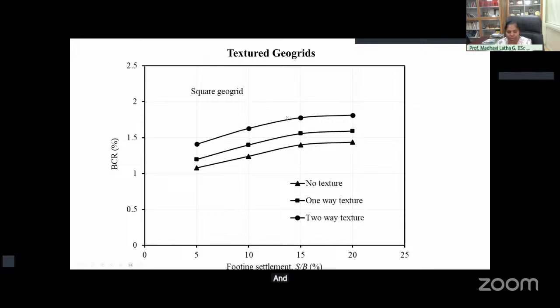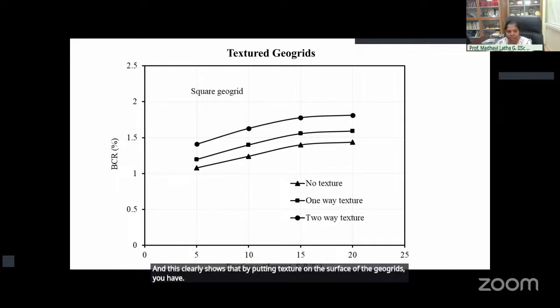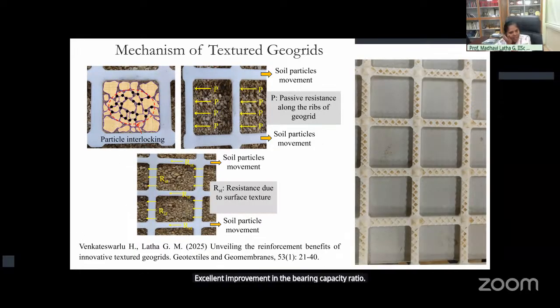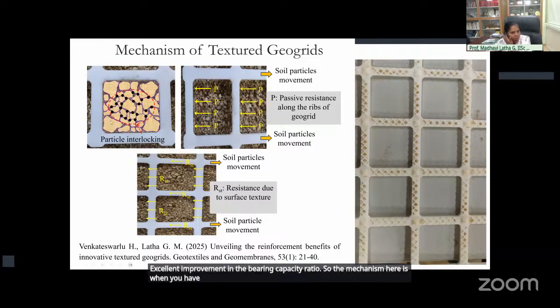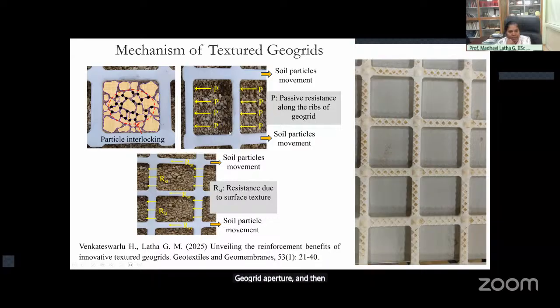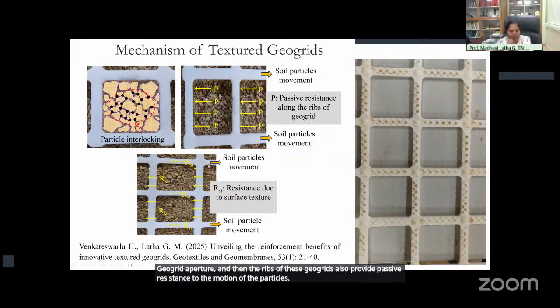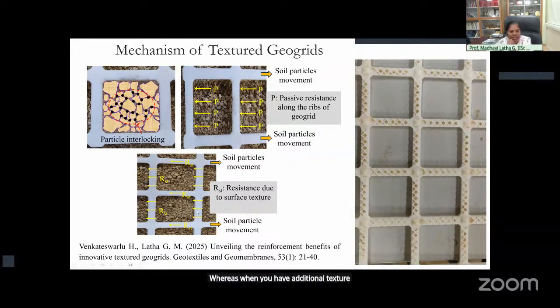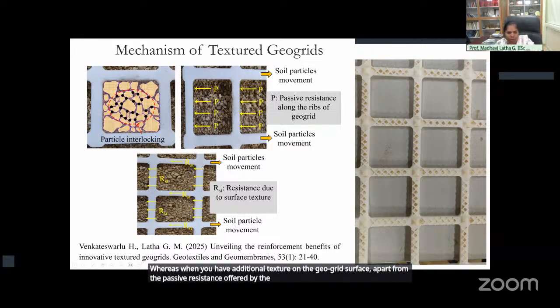And this clearly shows that by putting texture on the surface of the geogrids, you have excellent improvement in the bearing capacity ratio. So the mechanism here is, when you have smooth geogrids, the kind of mechanism you can expect is particles get entrapped and interlocked within the geogrid aperture. And then the ribs of these geogrids also provide passive resistance to the motion of the particles. Whereas when you have additional texture on the geogrid surface, apart from the passive resistance offered by the ribs, you also have resistance due to surface texture.